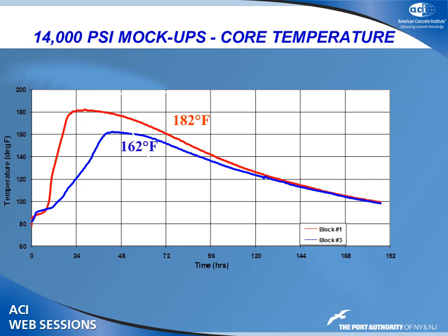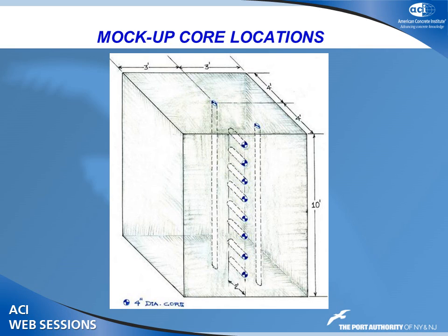And here's what we did. We actually took a vertical core in the middle of the slab, one foot from the edge, and we took some horizontal cores. Again, reading the 214 document, horizontal versus vertical, center versus edge. Is there a difference in the results? And again, we're the Port Authority. We collect tolls, limited resources. Let's core away. And here's what we got.